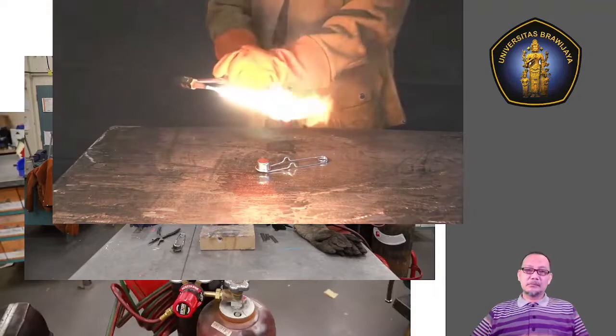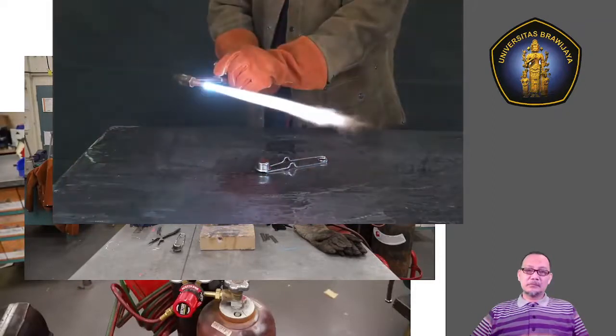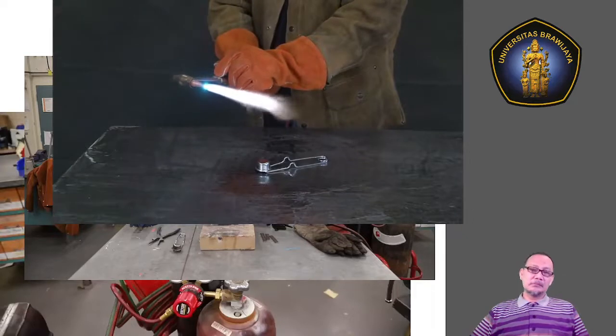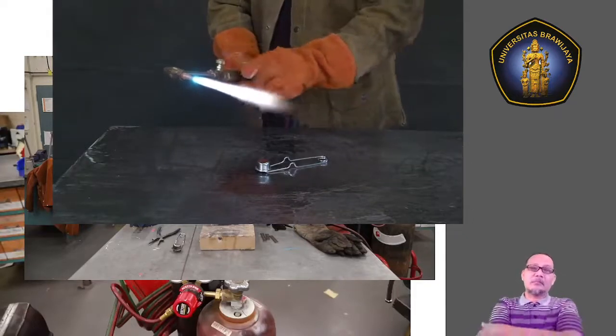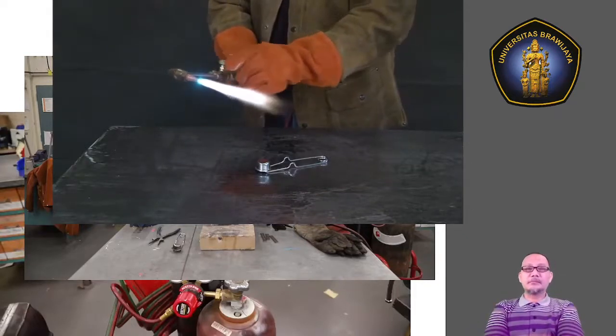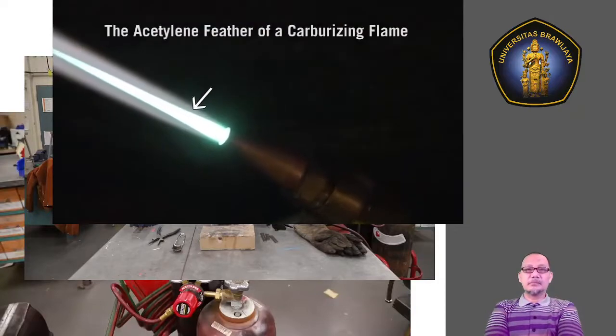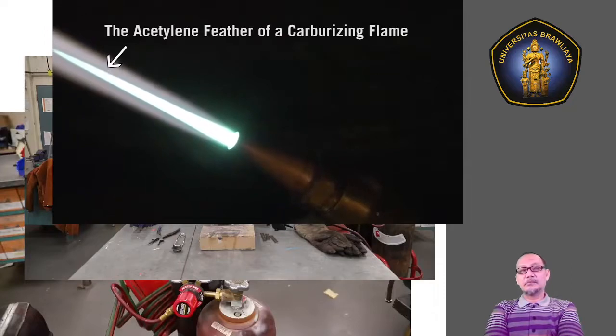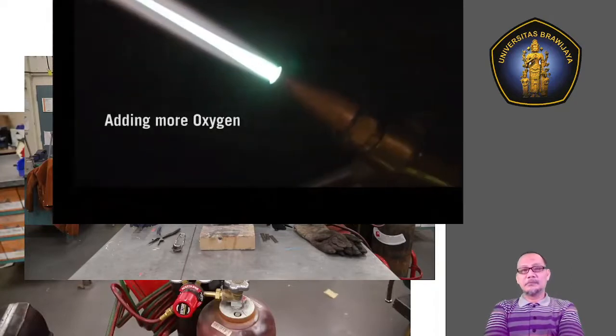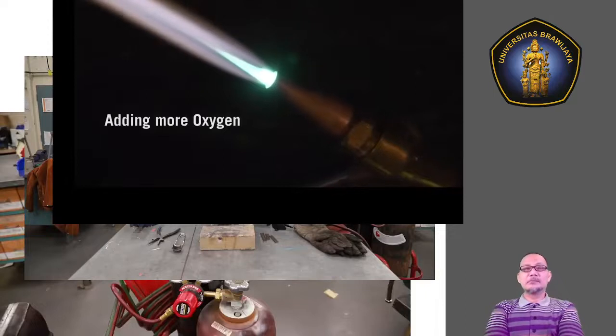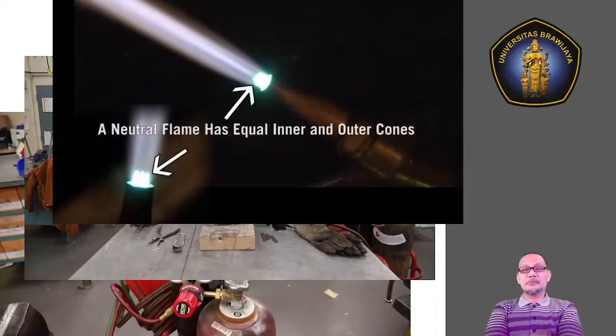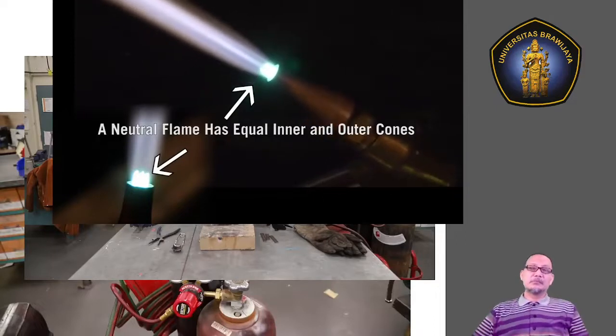As you add oxygen, the preheat flames turn blue, and you'll begin to see bright blue inner cones and lighter blue to white outer cones. At this point, the flame is still carburizing, which you can tell by the characteristic acetylene feather. Continue to add oxygen until the acetylene feather disappears and the outer cones become nearly equal with the inner cones. You will hear a slight hissing sound.